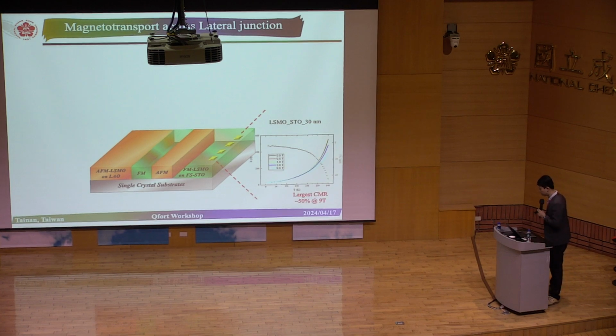Okay, so let's take a look at what we have. This is a typical magnetic transport measurement. You measure the resistivity versus the temperature as a function of magnetic field. You will see that when you apply a larger magnetic field, the resistivity goes down. So this is the typical LSMO we have.